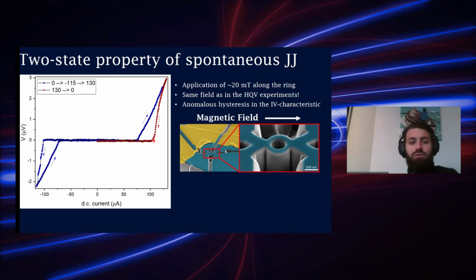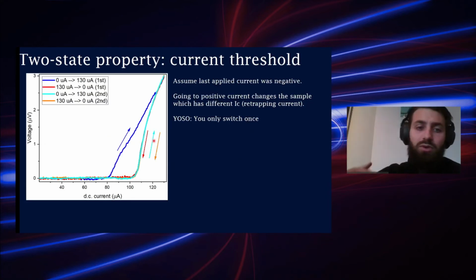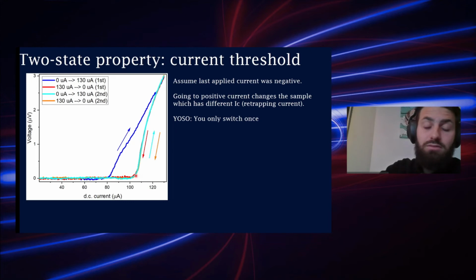We started playing around with this more, and when we wanted to repeat this experiment on the positive bias, we found that once we switched from the low critical current to the high critical current, we are stuck in the high critical current state. After switching between one and the other, you will always find a high critical current and a correspondingly higher retrapping current. You only switch once, and the only way to reset this is by going to the negative bias again.